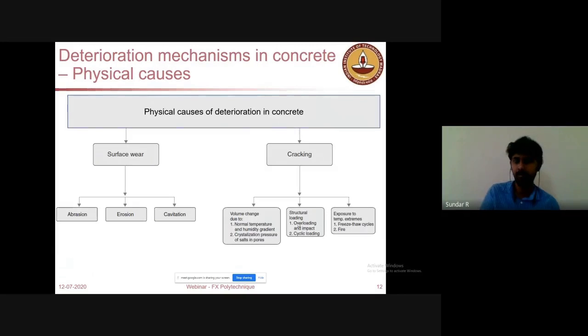Now we will see the deterioration mechanisms in concrete. This is very important because you need to think about long-term durability when you choose a material. There are physical causes for deterioration in concrete as well as chemical causes. The physical causes are predominantly erosion, abrasion, and cavitation. This surface wear can be observed in concretes in the spray or splash zone of water, or, for example, concrete roads which will be severely eroded and abraded by the tires running over them. There you should consider the physical causes of deterioration and take adequate measures.